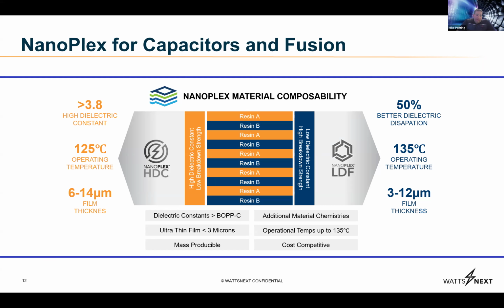So that's one flavor we have, and you can get it in different thicknesses and sizes and lengths, just like you can of the normal capacitor film. We also have a flavor of nanoplex film we call LDF, which is low dielectric loss. This is an ultra low loss equal to the best current dielectric material, BOPP. But again, it operates at a much higher temperature. So you're looking at extending the lifetime of capacitors or avoiding derating some of your materials that go into more extreme conditions. LDF can operate, again, with similar losses to the industry standard BOPP up to 135 C or higher, and it comes in multiple thicknesses similar to the state-of-the-art materials. So by changing the polymer materials that we're putting in resin A and B, we can get these different twist cone flavors that people can try in dielectrics.